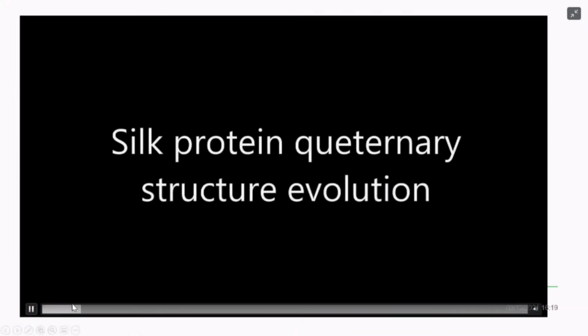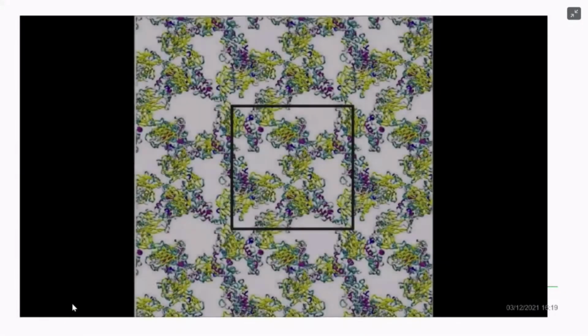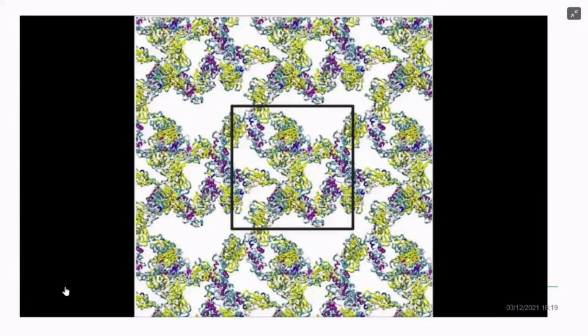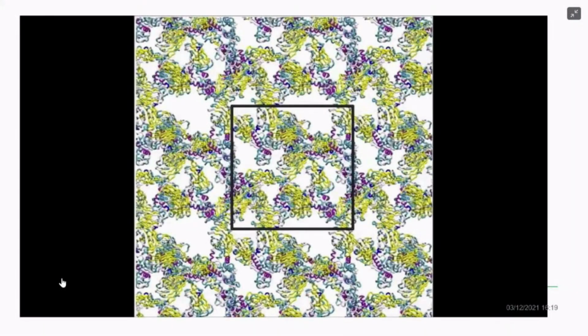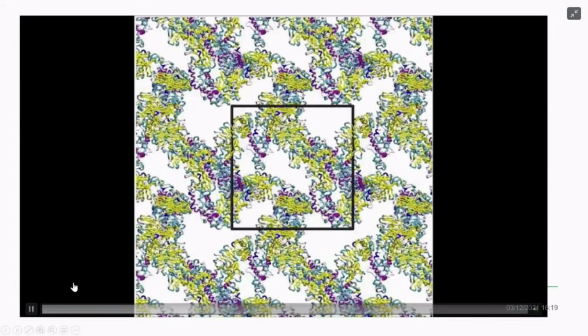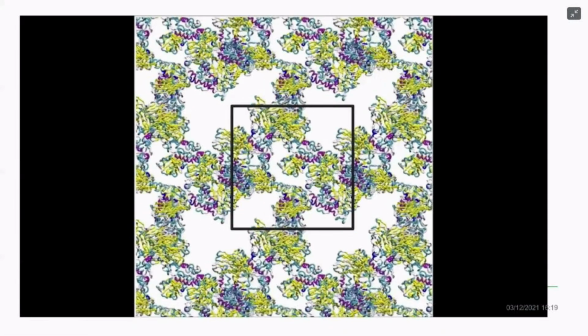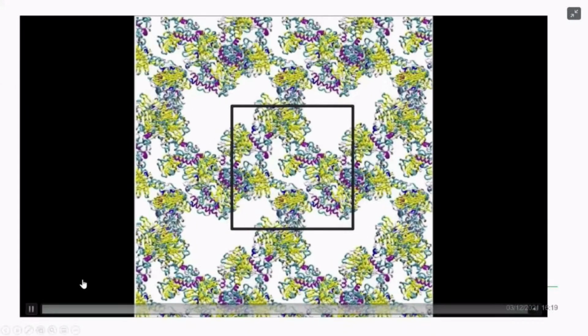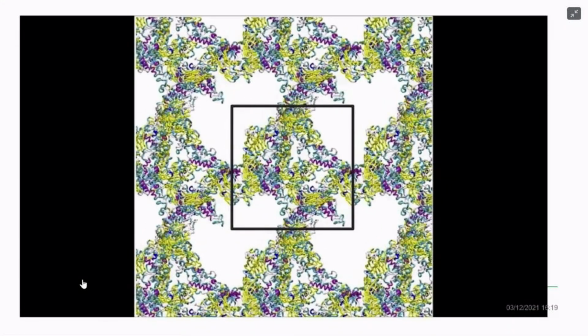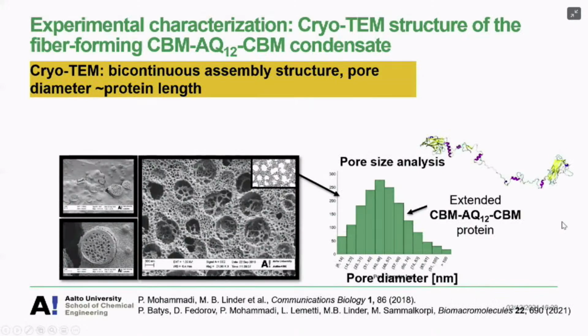So then how does this look in practice? This is how the protein network evolves in a molecular dynamics simulation in atomistic timescale. And what you probably see from here is that the end units are pretty attached. They are tightly holding together. And then the alpha helical parts are more flexible. They are the ones that are causing that fluctuation there. And no, it's not fully reorganizing during the simulation timescale. Then going back to the actual experimental finding, this was the finding: a porous structure and pore size approximately the protein length.